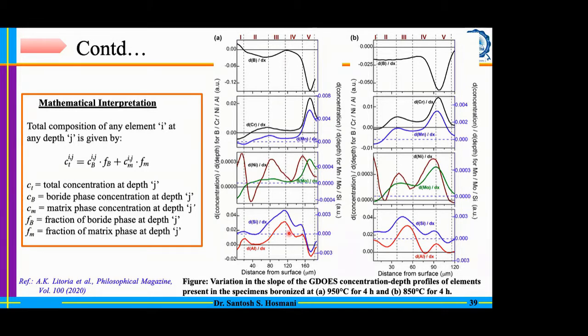And for that purpose, we took a mathematical interpretation. What does this simple interpretation say? You have a total concentration. The total concentration of an element at any depth is basically a combination of the chemistry of the boride as well as the chemistry of the matrix, along with the fraction of boride and the fraction of matrix. A simple lever rule has been applied here. And what is the outcome of this interpretation? During the boride growth, there are two categories of elements. Some of the elements are entirely rejected; I will call them set number 2. And the elements which are accommodated into the boride, I call set number 1. So, set 1 elements.